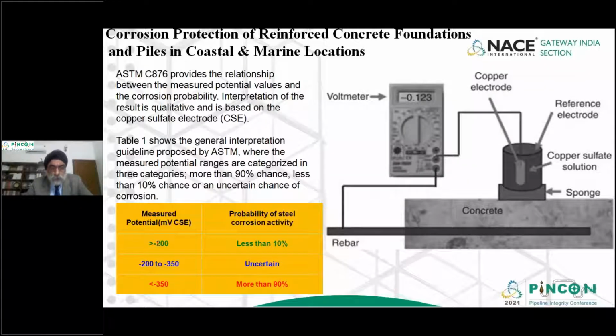more positive than minus 200 millivolt, the probability of steel corroding is less than 10%. If the rebar potential is more electronegative than minus 0.35 volt or 350 millivolt, then the chance of steel corroding is more than 90%. Within 200 and 350 millivolt, it is uncertain if the steel is corroding or not. So by doing this simple test, we can really find out if the rebar within the concrete is in a passive zone or in an active zone as far as corrosion is concerned.